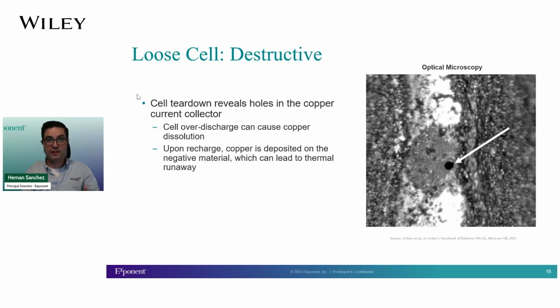You were dissolving the copper, and then if you were to cycle that cell, you could get those copper dendrites that were shown in the previous talk that can short the cell and produce failures. So once again, the non-destructive tells you there's something to look at further. Sometimes it's enough, but more often than not, you do want to follow up with some type of destructive testing to really dig deeper into the details to understand the failure mode and to make your product safer.